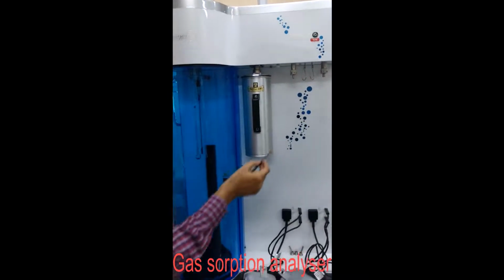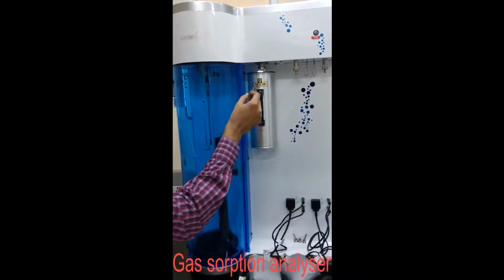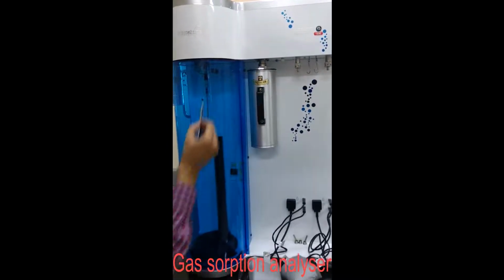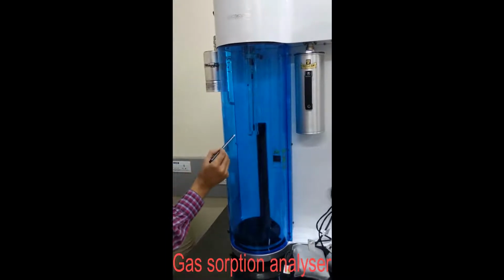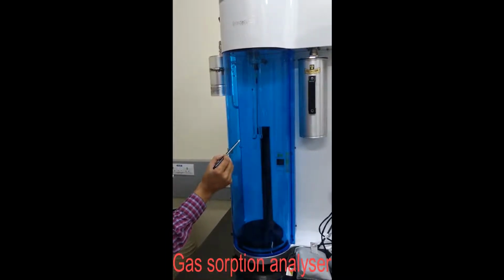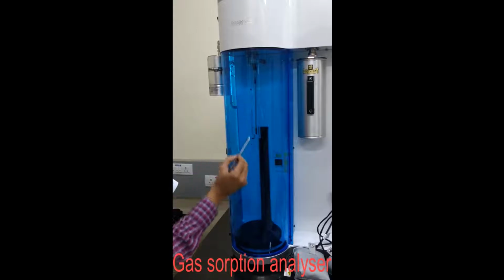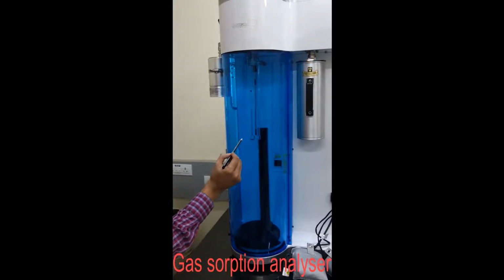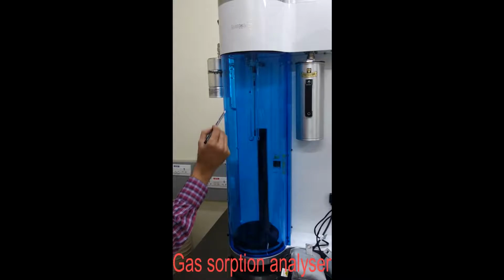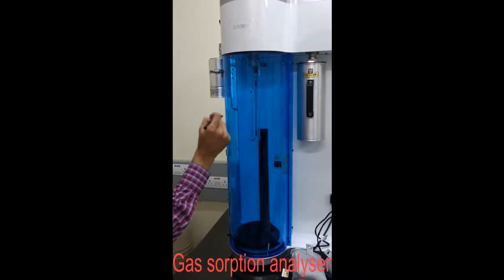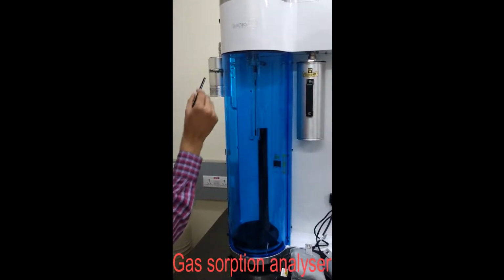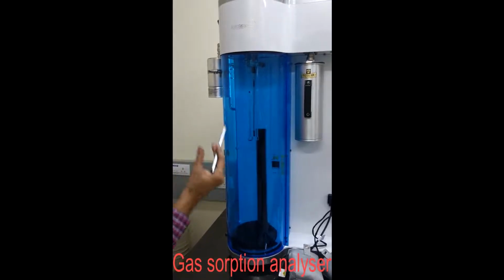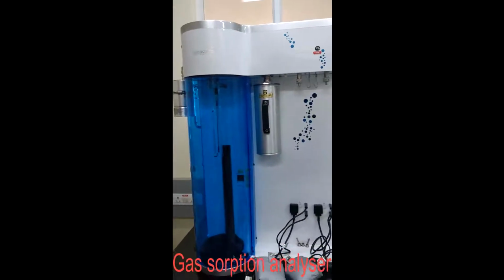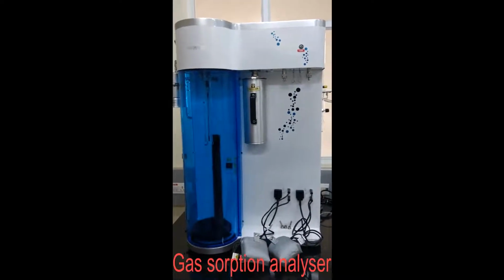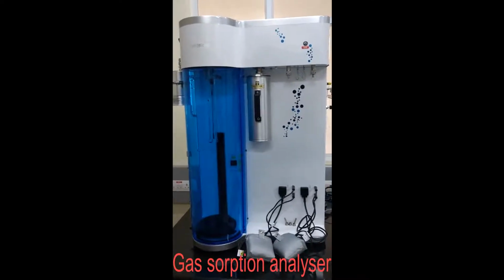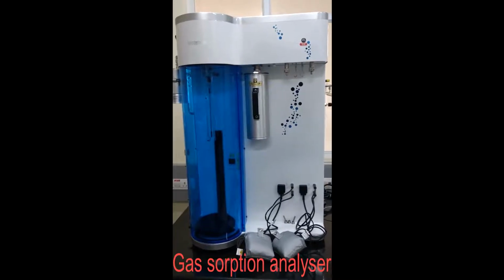So here you can see we have a standard sample where the dewar is there, and you can also see the sample which is being measured is kept here in this quartz tube or glass tube, and a standard sample is here which serves as a reference, and compared to that, how much the sample is absorbed can be measured using this equipment. Usually the units for surface area will be meters square per gram. Along with that we can get pore size and pore volume respectively. The cost of this equipment is nearly 49 lakhs.